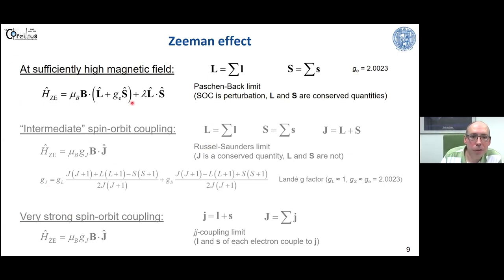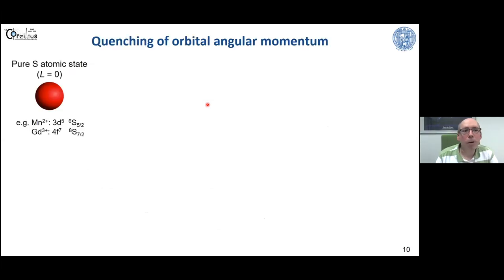But let's go back to this high field limit, practically, where the spin orbit coupling is only a perturbation, because this is the only system where we can actually use in DNP in the end. Now, it would be great if we can get rid of the orbital momentum, because then we had a spin only case practically, and then we can have an isotropic g factor close to or even exactly at the free electron g factor 2.0023, and we would have an isotropic EPR resonance and we would all be happy. How can we reach such a state or nearly reach such a state?